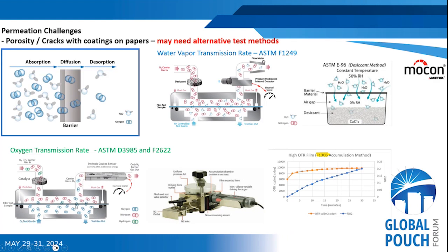And just what I mentioned before with the water vapor, if there are any holes or cracks or anything with the paper, we can get erroneous results. You can actually push oxygen through, overrange our sensor, and you just get a very low result. Sometimes, if the equipment isn't set up right, you might have a little bit higher flow over here, and you push the nitrogen through this way, kind of diluting it, and you get an artificially low result. So any material that isn't really hermetic, that isn't a great barrier, isn't really well suited for this kind of gas flowing instrumental test.